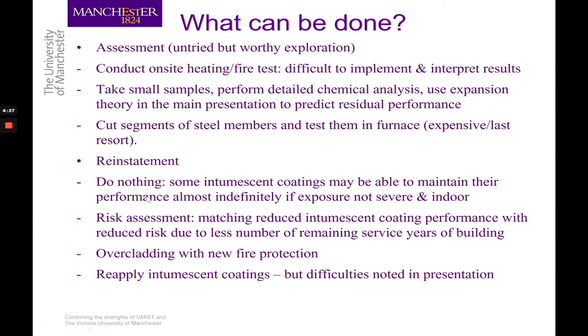One is to conduct on-site heating fire tests, which can be done, but it's a bit difficult to implement on site. More importantly, the results are difficult to interpret because it's very difficult or impossible to mimic the design or required heating condition on site. The second method could be using the method which I mentioned in my main presentation, by prediction. If we can take a small amount of intumescent coating from site and do some chemical analysis to obtain the fundamental properties for predicting its performance. This is worth doing, but hasn't been done before.